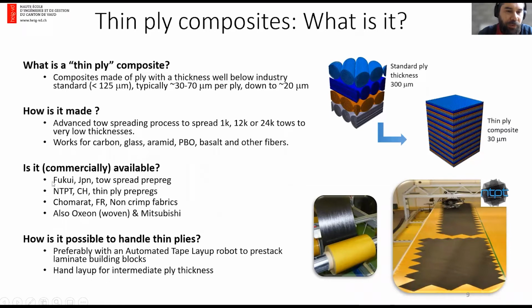It was first developed in Japan, in the center Fukui, but we also worked very closely in Switzerland with NTPT, North Thin-Ply Technology, which is specialized in Thin-Ply prepregs. There's also Chomarat in France and Oxeon, which are also producing Thin-Ply non-crimp fabrics or woven fabrics. The difficulty when ply thickness is reduced this much is that if we handle it as a prepreg or a textile, it's not very stable. So it's ideally suited to automated tape layup systems and robotic processes, because laying it by hand is relatively difficult.